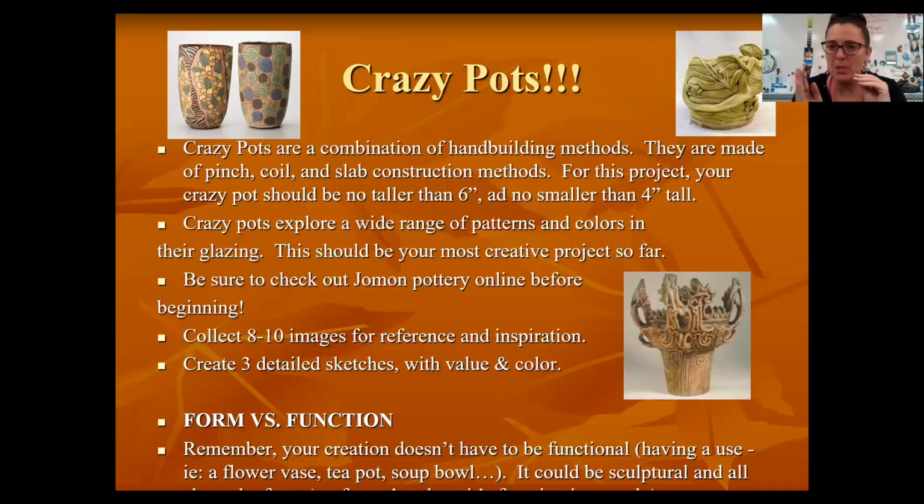We're going to make sure we score and slip anytime we add clay to clay, and I'll do a demo in class. If you just make this little donut and stick it, make this little donut and stick it, as soon as I go to lift that, it's going to fall apart, and it's not even going to make it through one lift and get in the kiln. And if it does make it in the kiln, as soon as I go to take that thing out of the bisque firing, I bet you $1 it falls apart. You've got to make sure you score and slip, okay? So I'll do a little demo to get us through.